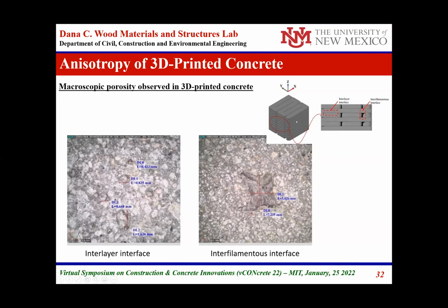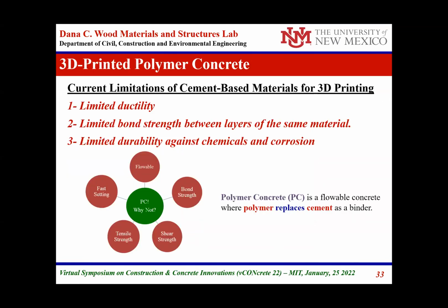In the Z direction, strength is lower because of the preferential interfilamentous interface, which could sometimes be connected, making the material weaker along the z-axis. However, while weaker, it is still stronger than similar concrete made of the same material but not 3D printed. So there is anisotropy in 3D printed concrete, but in all directions the concrete is stronger than the non-3D printed case of the same mix.